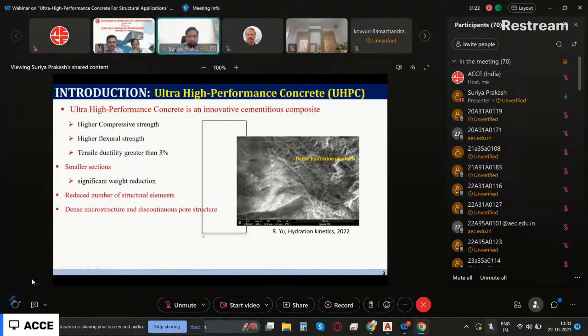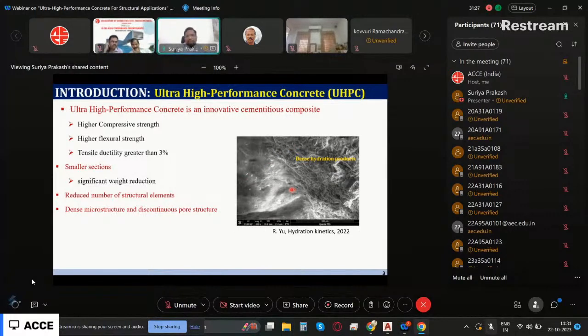Now, another important thing is because we are going to use very fine material. When cement reacts with water and the aggregates, you form hydration products or calcium silicate hydrates. That is what gives strength to the concrete, right? In a regular concrete, the weak link is always what we call the interfacial transition zone. That is the interface between the aggregate and the cement paste.